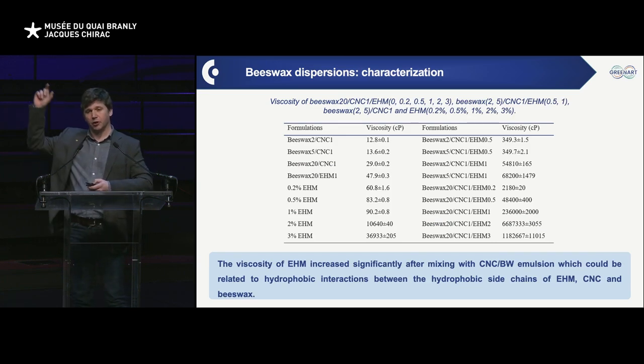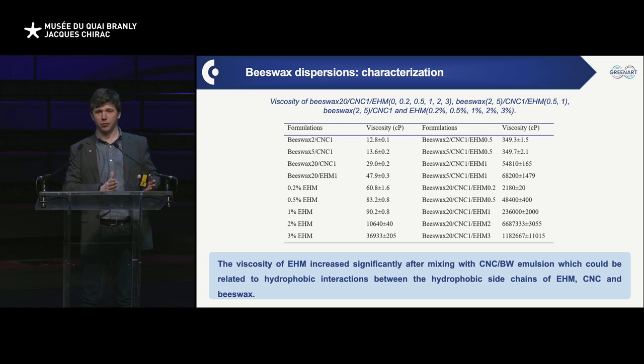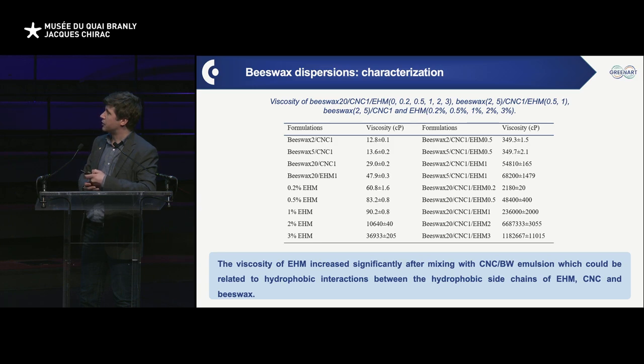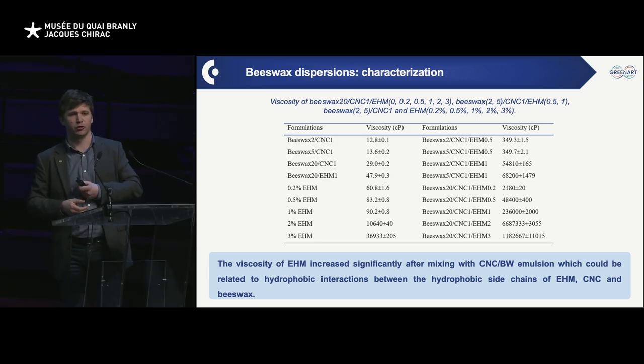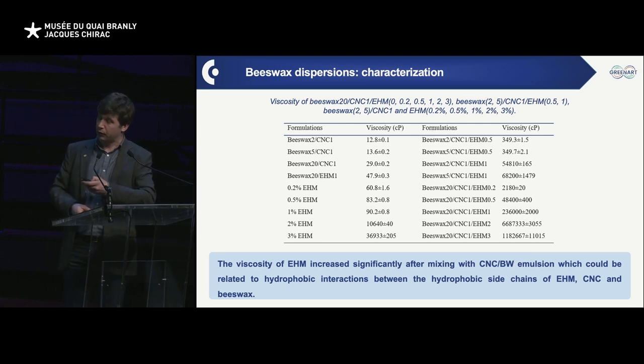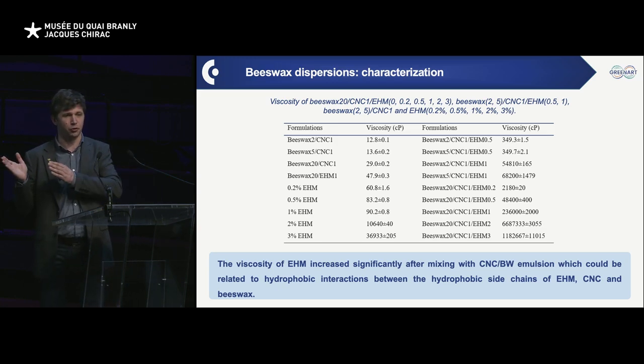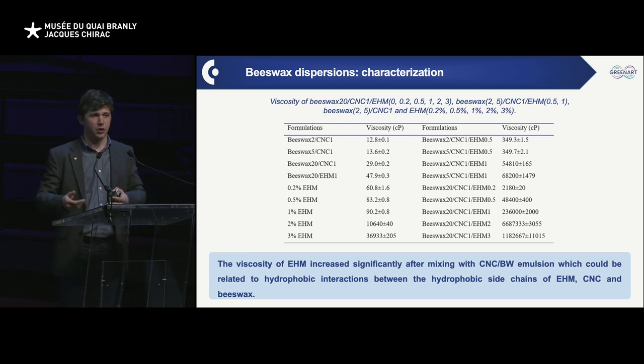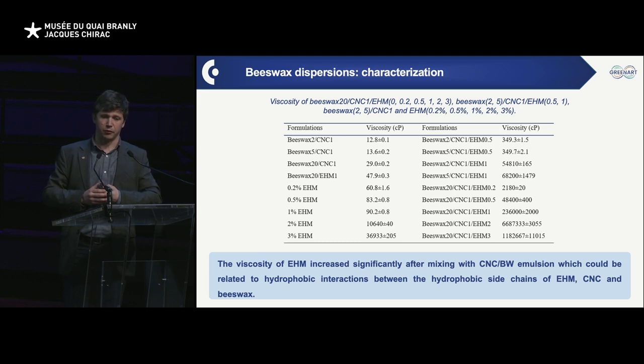Well, of course, the original idea when introducing the EHM was to regulate the viscosity of the system. This is a viscosity modifier extensively used in industry, in the coating industry. And here what we did was pretty simple. These are the original emulsions with 2%, 5%, 20% beeswax content, the CNC content is the same. The viscosities are well below 40 centipoise. But as soon as we start introducing the EHM, like we do over here, we multiply the viscosity by very large factors. So we get from something that is runny to something that is very thick, to an extent that if we do the right formulation, we can have a viscosity that is close to a paste. It's nearly close to butter, as compared to a fluid that you can brush or even spray. So we can regulate very carefully and very accurately the properties of the system simply by adjusting the concentration of the cellulose derivative while maintaining the concentration of beeswax relatively high, which is useful.